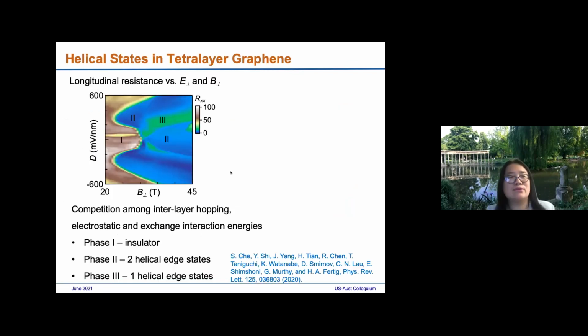All right. So this is actually just one slide. We're just saying we also see the helical edge states in tetralayer graphene. This is four layers. This work is done with Professor Fertig, Murthy, and Shimshoni. This is a similar phase diagram as I showed before. At charge neutrality point, we're plotting the resistivity as a function of displacement field and magnetic field. It's a pretty striking phase diagram that looks different from the trilayer, right? So now we can see phase one.